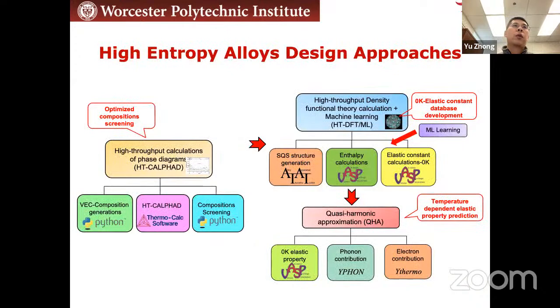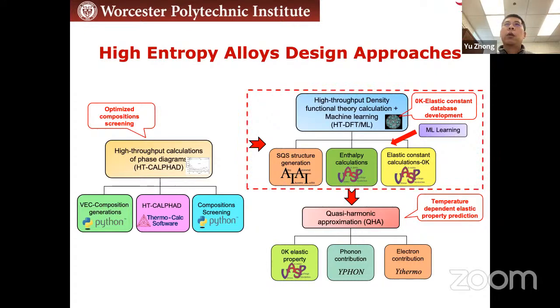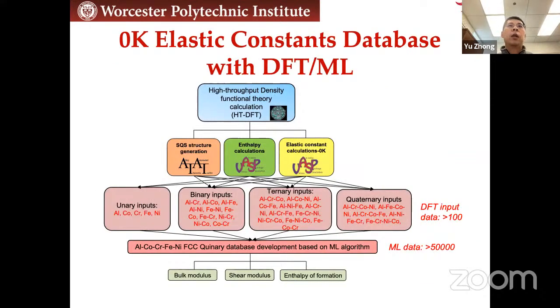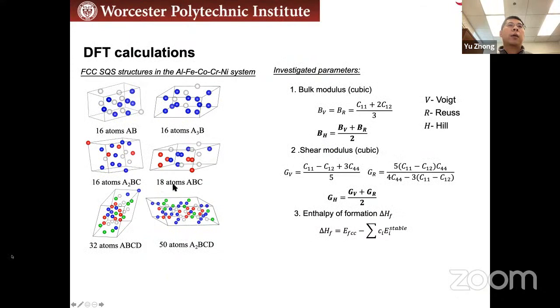By solving these phase stabilities, we still need to figure out the mechanical property. So how do we do that? At first we want to know the 0K mechanical property, and this is what we have done. We have developed these high throughput DFT calculations, and combined with machine learning, we can make predictions of the bulk modulus, shear modulus, those kinds of things. These are the supercells we have created to do the calculations, and the formula here shows how we can calculate the bulk modulus and shear modulus.